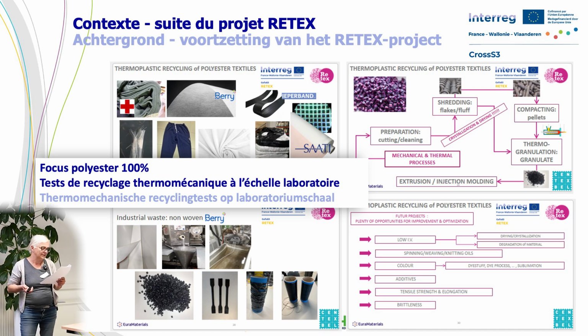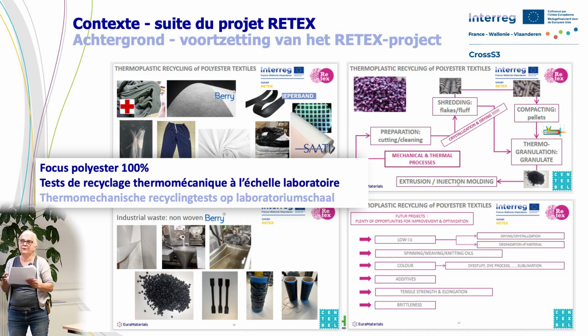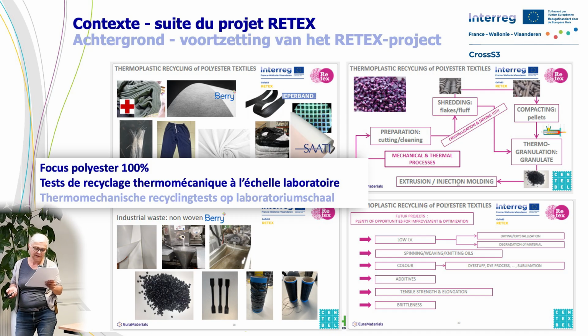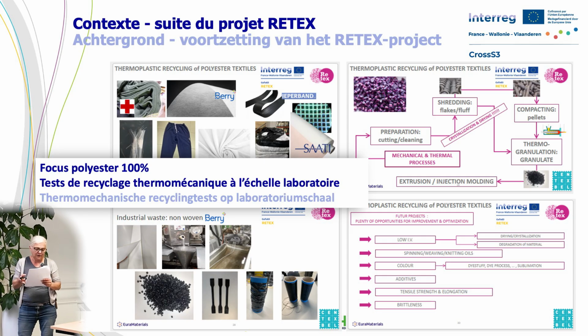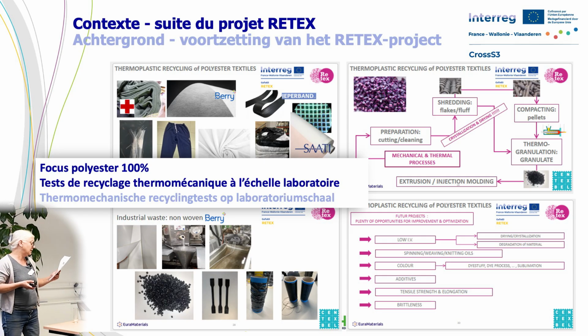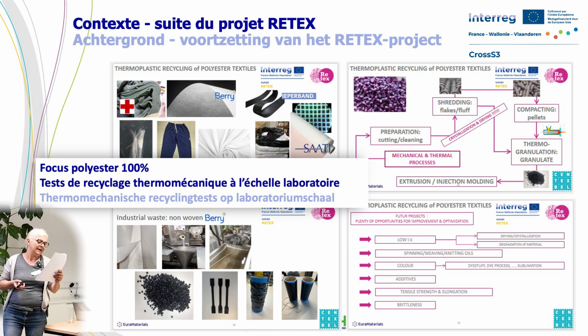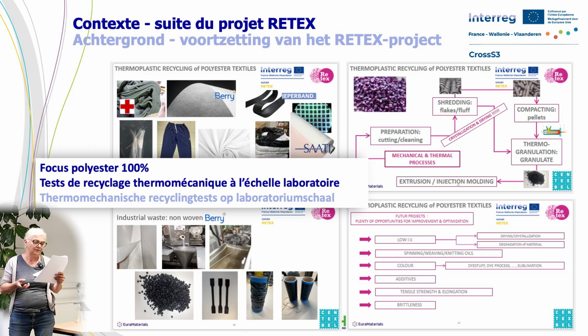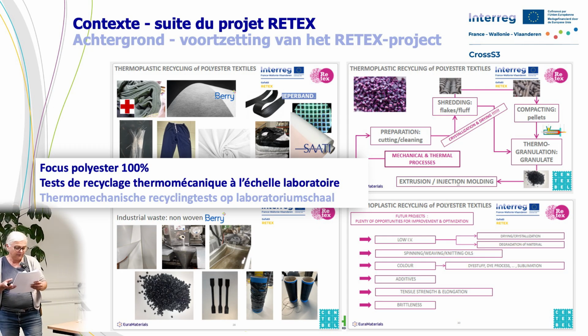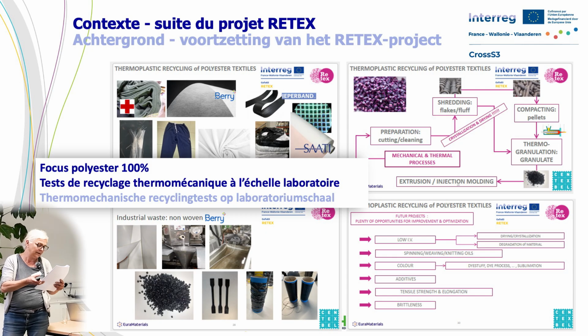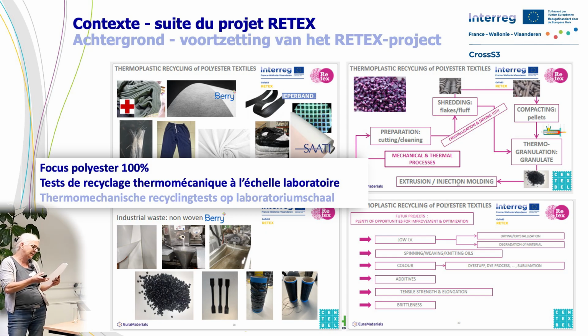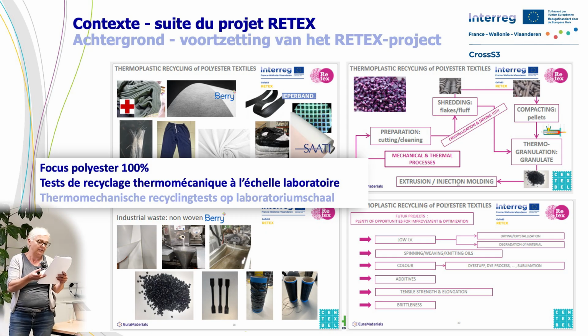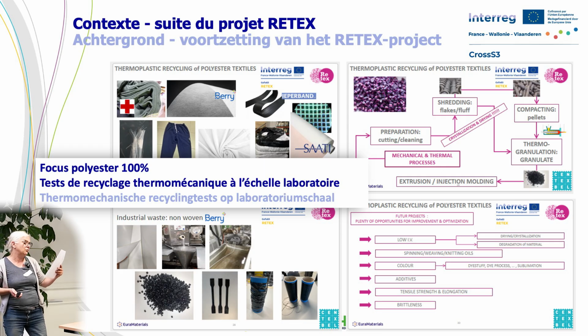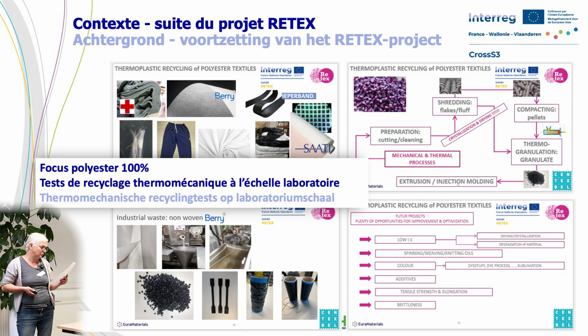And then we identified some barriers. First, rheological degradation throughout the process: shredding, compaction, pelletization reduce the intrinsic viscosity of the polyester, making the material more fluid and then fragile once extruded. A second barrier was drying, because once shredded and compacted, textile fibers cannot be thoroughly dried using current equipment. However, insufficient drying directly accelerates the degradation of the viscosity, making further development impossible.